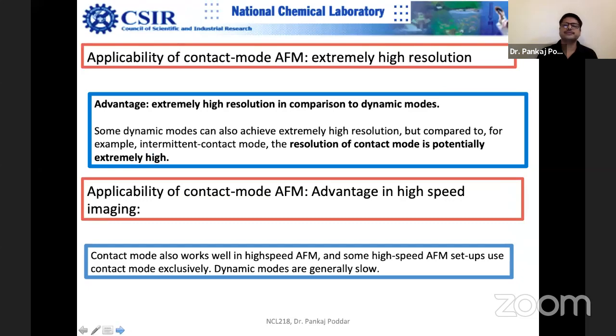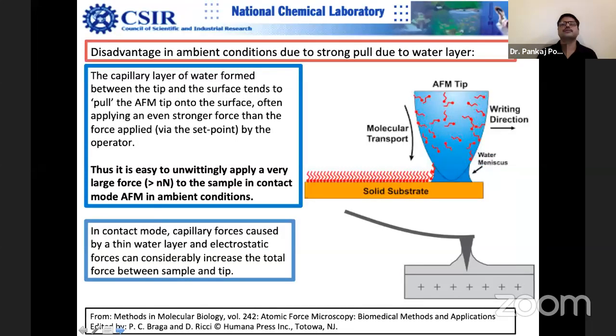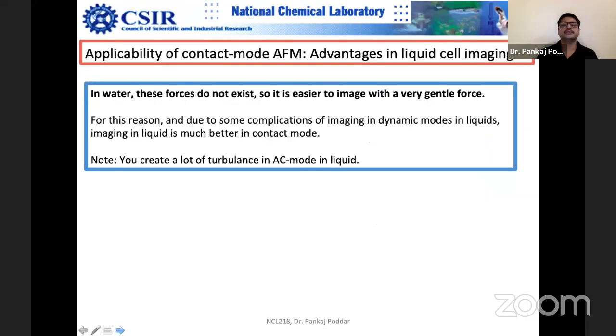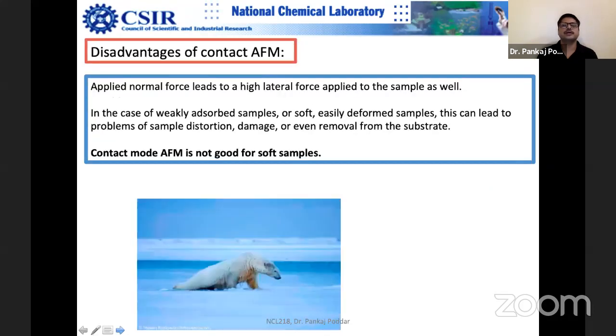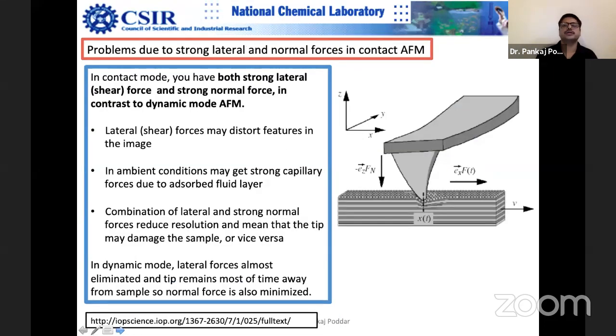So contact mode is basically high resolution, and there are problems because of the capillary forces. As we mentioned, in the rainy season like this, contact mode imaging on hygroscopic samples is quite difficult. Another disadvantage was that you have both lateral force and normal force on the sample. So if the set point is too high, if you are tracing the sample too close, you're applying too much vertical force, then essentially the tip also gets blunt.